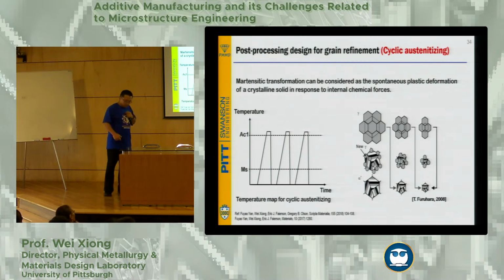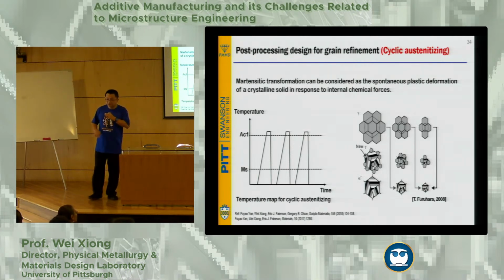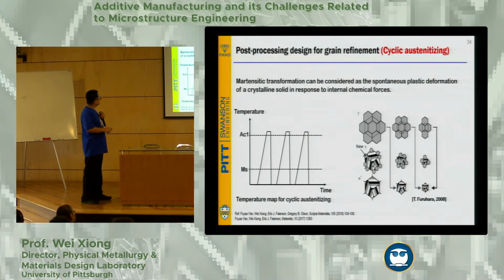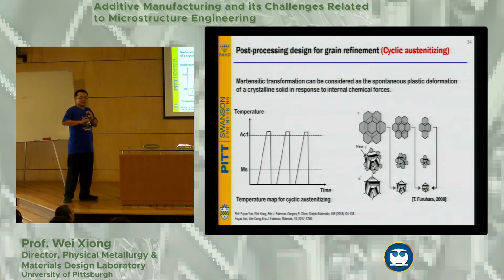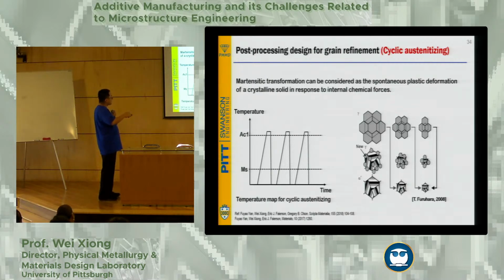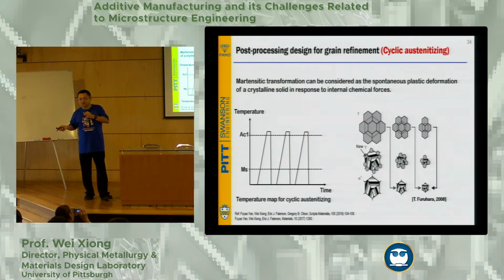So if you do casting and so on, you receive the microstructure. What you can do is heat it up and let the microstructure homogenize and form austenite, then you quench it and start forming martensite below the MS temperature. Therefore, you can do a cyclic cooling and heating process.